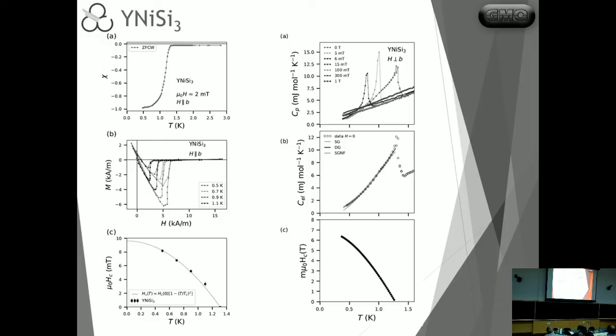And this is very rare to see, type 1 superconductivity in a ternary intermetallic. Type 1 superconductivity is almost exclusive to the elements, and then maybe a few compounds here and there. There's probably less than a handful of compounds that are known to have type 1 superconductivity.